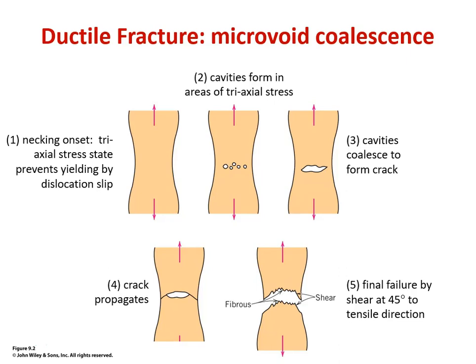And this is the onset of where we'll start to see a triaxial stress state. So we no longer really have uniaxial applied stress in that necked area. Because of the presence of the neck alone, we now have stress in three directions, effectively along the sample and then radially. This is very important because this triaxial stress state is making it very, very difficult for dislocations in the necked area to keep moving. If dislocations can't move, the material effectively gets stronger, but if dislocations can't move and we just keep applying stress, eventually energy is going to have to be dissipated in another way. And that way is by forming a surface, which is, of course, the next thing that happens.